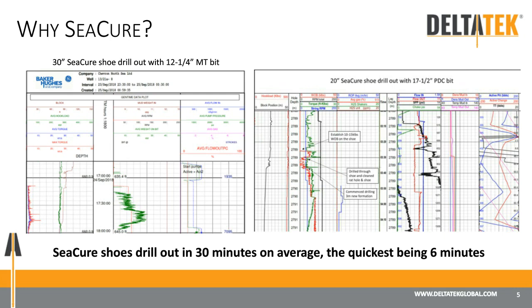I mentioned about the slim hole drill out opportunity, which SeaCure helps reduce risk of cement blocks falling in around the BHA. This is a drill out on the left that we can see from this, a 12.25-inch assembly drilling out a 30-inch. And a little over 30 minutes, which resulted in all of the operational objectives of that well being achieved.